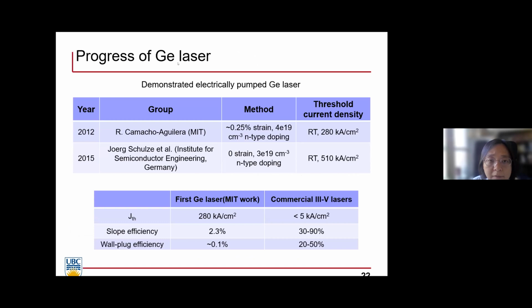So really, the progress of germanium lasers: two demonstrations, and the performance. If you see the performance table, the threshold current density is pretty high. It's much higher than commercial lasers, and the efficiency is at least 10 times lower. And wall plug efficiency is even lower. So basically not a good performance yet.